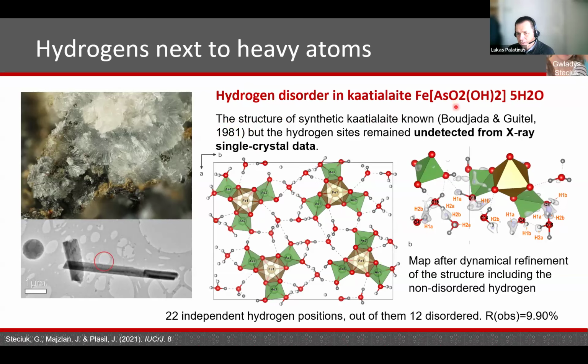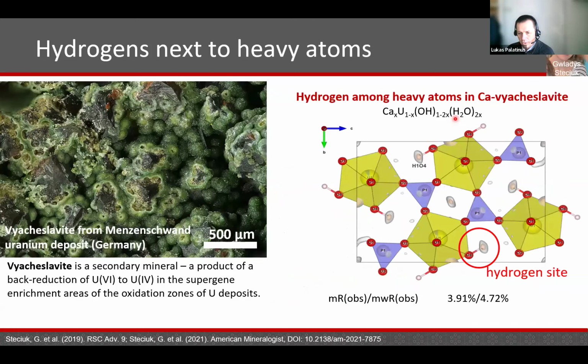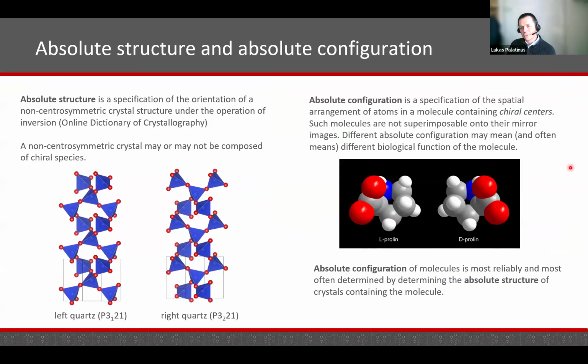And if hydrogens next to arsenic still do not impress you, then there is the structure of Viacheslavite, yet another mineral, where Gladys Stetsiuk, our colleague, is specialized on mineralogical samples and their analysis by electron diffraction. So this is a uranium-containing mineral. So this atom here is mostly uranium, surrounded by 10 oxygens. And in this case, one of the oxygen atoms has a hydrogen atom bonded to it. And again, you can clearly see the site of the hydrogen in the difference map. So that was the story of hydrogen atoms and a demonstration of how efficient electron diffraction can be in spotting hydrogens.